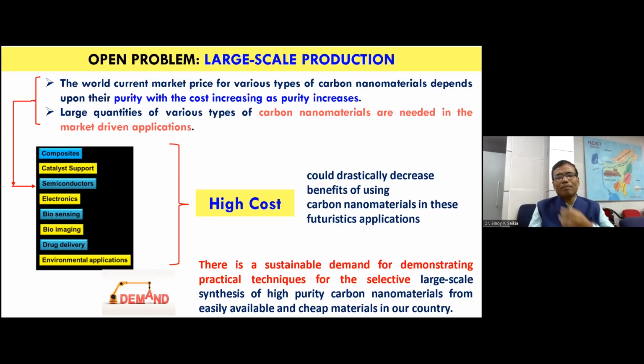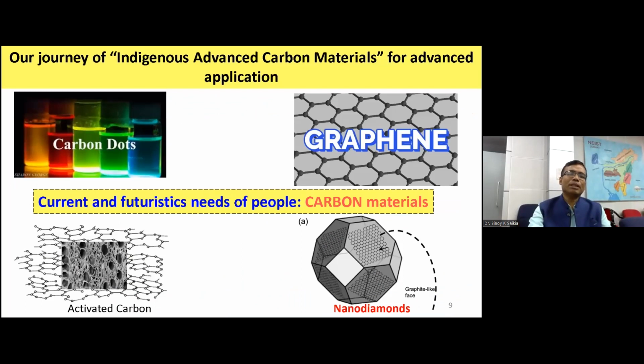There's lack of attempt in this line. So this was the curiosity we started in 2016, 17 onwards. Then we found that yes, this coal could be a major precursor material for synthesis of carbon dots, graphene, activated carbon. This is well known. Activated carbon is well known, but these nanodiamonds, the three: carbon dot, graphene, and diamonds could be the source of